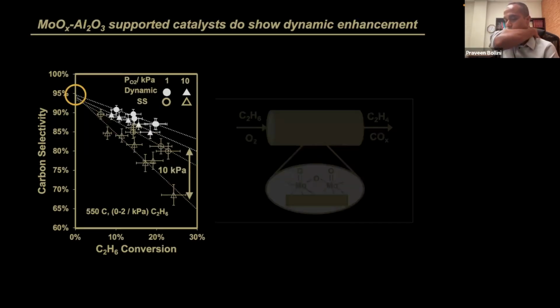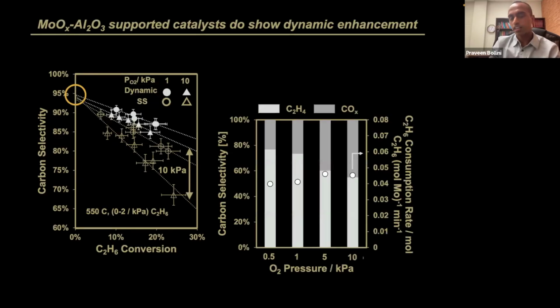And you can, in fact, exaggerate this effect as well at high conversions, or in this case, when you increase your oxygen pressure from 1 to 10 kPa, you're able to increase this difference between ethylene selectivities for the dynamic and the steady state cases. So higher oxygen pressures make this selectivity improvement exaggerated even more. And again, this is some rate data where you get information about your reaction network, and specifically what I'm trying to show is that there's one reaction which is an unselective ethylene over-oxidation reaction that is oxygen pressure dependent, and by using chemical looping, you're able to mitigate the conversion of ethylene to CO2, thereby increasing ethylene selectivity.